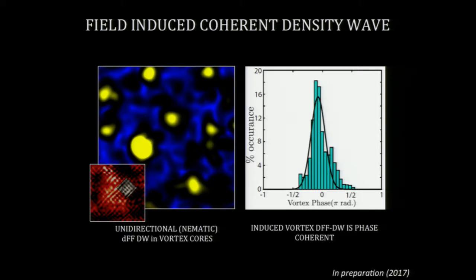And furthermore, when Jennifer Hoffman looked at vortices and saw the periodic spatial modulation, we went back and looked and saw, in fact, within the vortex cores (I'm just showing the amplitude of these modulations) there really is one of these D-symmetry density waves inside them. And furthermore, oddly enough, and we can't explain this part yet, if you were to look at a density wave inside a vortex core here and then one here, they're perfectly in phase with one another. So if I were to follow the modulation, it perfectly matches up with this one. Even though they're 10 nanometers apart, there seems to be some information which makes the spatial phase of this one and this one match up. So there's something underneath all that which is coordinating the system.